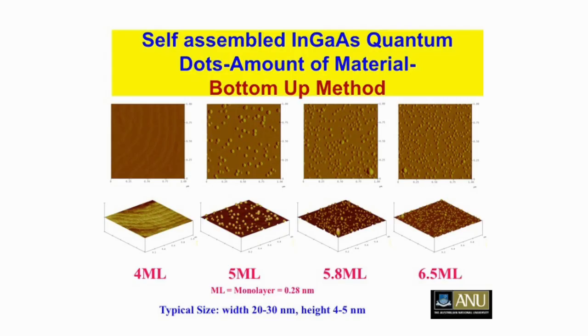In my own laboratory, we have been doing one atomic layer by one atomic layer deposition. Here I'm showing you monolayers. One monolayer is about a quarter of a nanometer. I've got 4 monolayers, that means about a nanometer. It tries to stay as a two-dimensional material. And if I put one more monolayer, suddenly they form into these so-called quantum dots. In fact, we demonstrated lasers made out of these particular devices. This is what we were doing in the 90s to mid-2000s, trying to demonstrate a wide range of devices like lasers and photodetectors and other things.